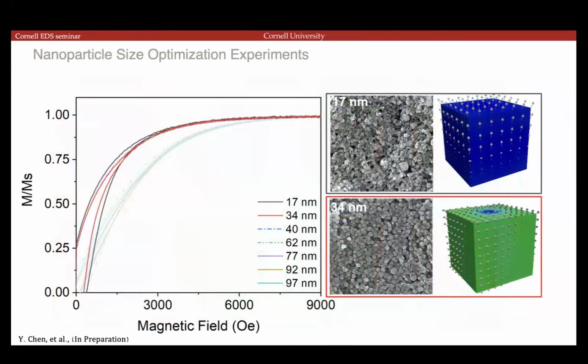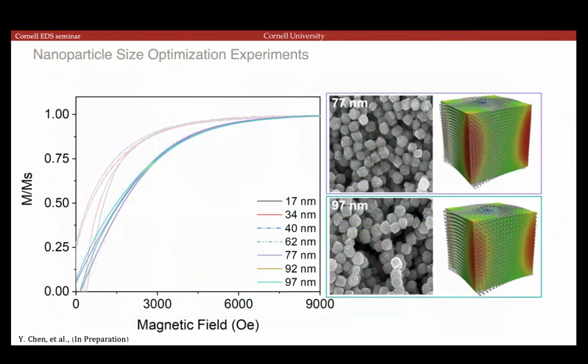This is a comparison of both experiments and simulations. So the curves on the left are the experimental behavior. You can see that the remanence is higher for 17 and 34 nanometers. These are the two smallest particle sizes that she synthesized. The one for 34 nanometers, we still thought it was going to start curling on itself, but it seems to have fairly high remanence still. And then any higher and it becomes multi-domain. You see the sudden drop in the remnant magnetization to near zero.